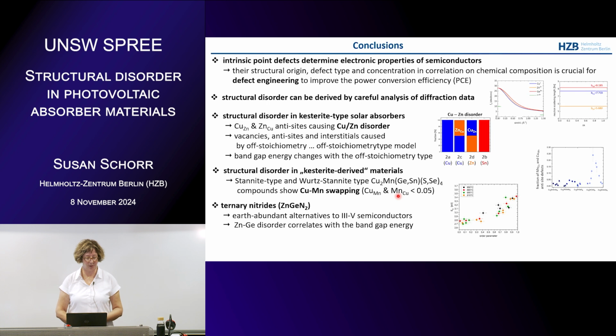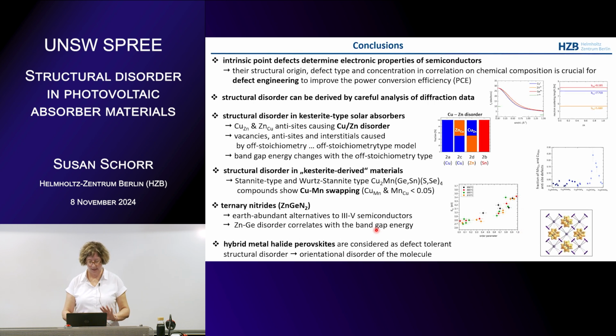I showed you our studies on the ternary nitrides, where we could really show, which was speculated in literature before, that the zinc germanium disorder correlates with the bandgap energy. And I showed you a little bit of our work on the hybrid halide perovskites. They are defect tolerant, but now you have an orientational disorder of the molecule, which is also important for the material. And I think it also leads to the low stability of the material because of these weak bonds and the weakening of the bonds you may have.